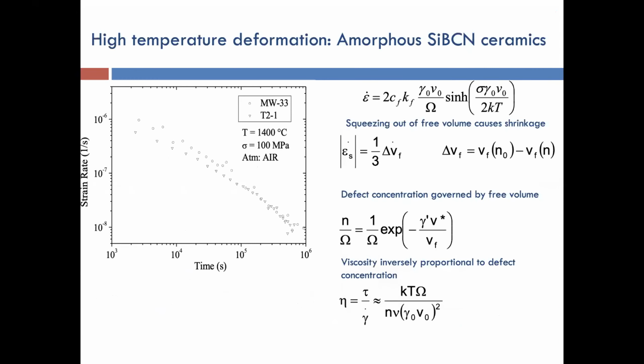And we investigate a lot of their properties, mechanical properties, and I will just show you the high temperature deformation properties of these materials, because these materials are used at extremely high temperatures and also coupled with loads. So we subject these materials to a constant load of 100 megapascals over a range of temperature. In fact, I have just shown you a prototypical example of one temperature, one load combination. Otherwise, typically we do at least three different temperatures at constant load, and at one temperature at three different loads. So at least you require 6 to 8 experiments to get some idea whether this material can be stable and can be used for an application over an extended period of time.